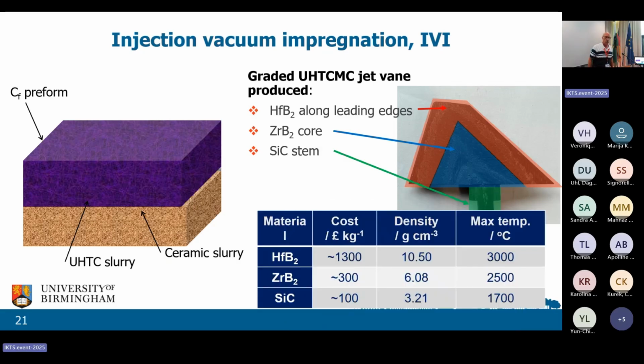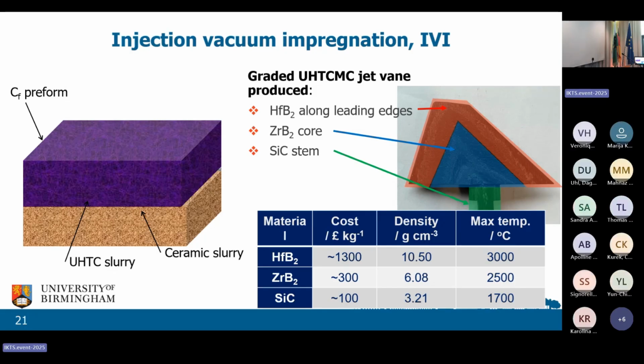And the reason why you want to do this, hafnium diboride, yes, it'll give you 3000, but it's 10.5 grams per cc. It's dense, and it costs about, I apologize, I've used pounds. Normally I would have remembered to convert that to euro, but that's 1600 euro per kilogram. Zirconium diboride, 2500, just over half, 60% of the density. We're now down to 300, call it 400 euro per kilogram. Silicon carbide down to about 1700. Again, we've halved the density. Now we're down to about 100, 120 euros per kilogram. So you can make big, big weight savings and you can make big, big cost savings by only putting what you really need where you need it.